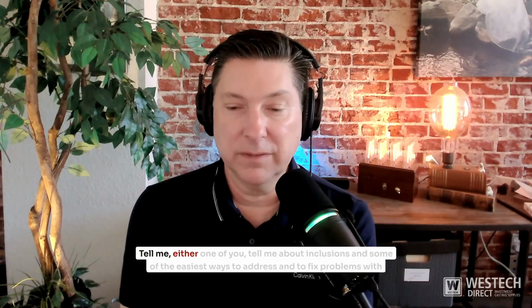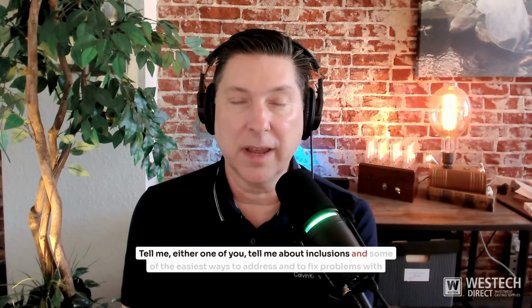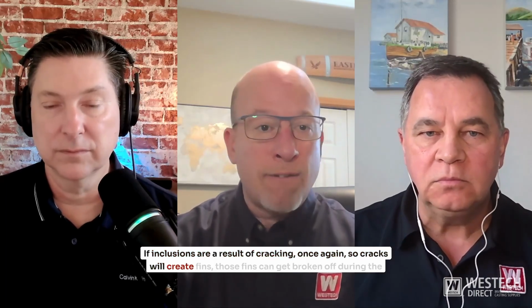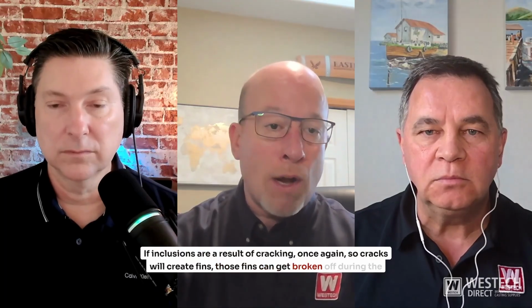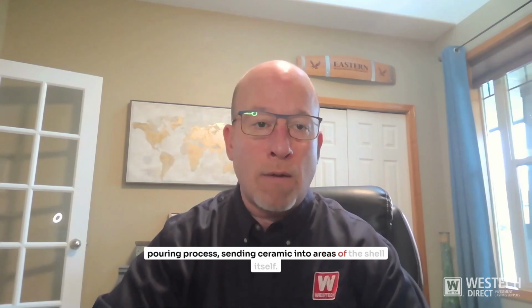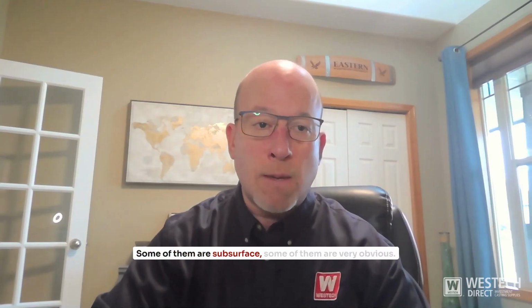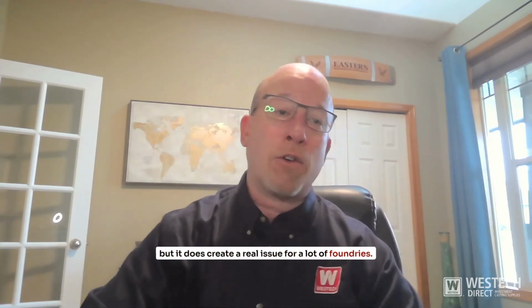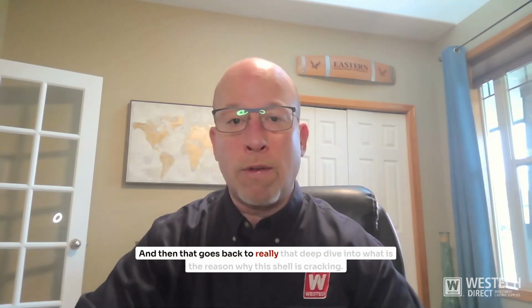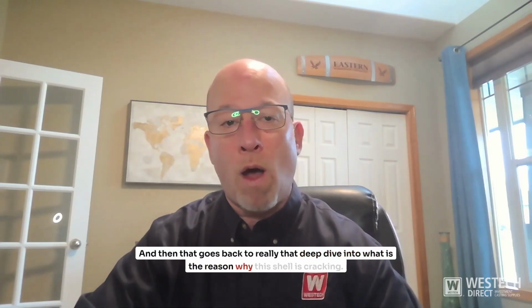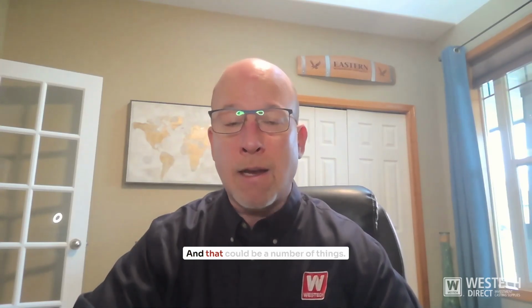Tell me, either one of you, about inclusions and some of the easiest ways to address and fix problems with inclusions. Inclusions are a result of cracking, once again, so cracks will create fins. Those fins can get broken off during the pouring process, sending ceramic into areas of the casting itself. Some of them are subsurface, some of them are very obvious, but it does create a real issue for a lot of foundries. And that goes back to really that deep dive into what is the reason why this shell is cracking. And that could be a number of things.